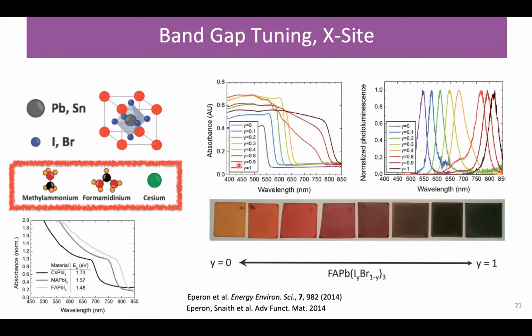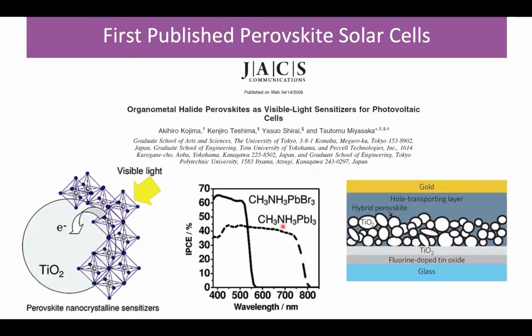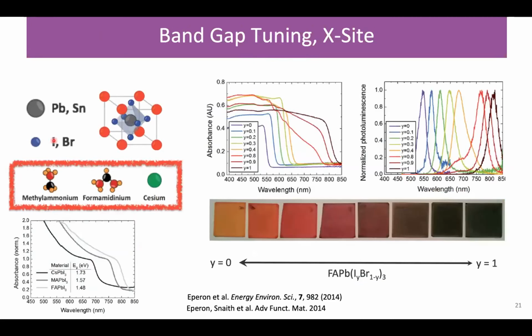But one of the other fabulous things about these materials is that in addition to having the absorption properties that we'd want, they're highly tunable. Now, these ones that Miyasaka showed are essentially lead bromide and lead iodide based. And this is methyl ammonium in this particular case. And it turns out as we tune the iodide and bromine, we can quite nicely tune the electronic gap. Not only that, this methyl ammonium, which was the one shown by Miyasaka, can be swapped out for cesium or formamidinium, and again, gives you a nice tuning of the electronic gap.